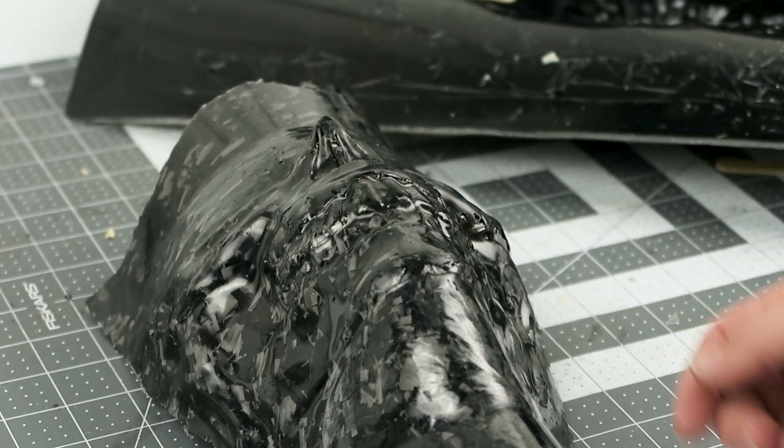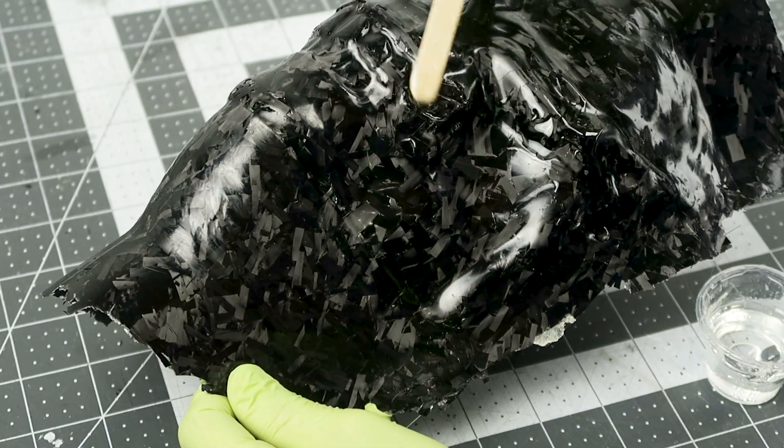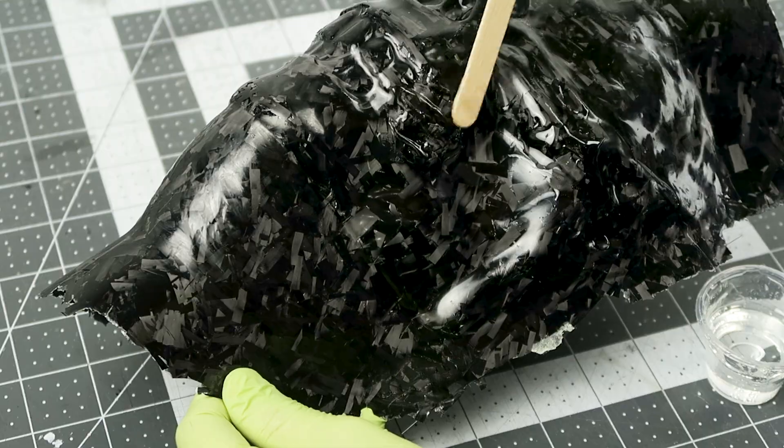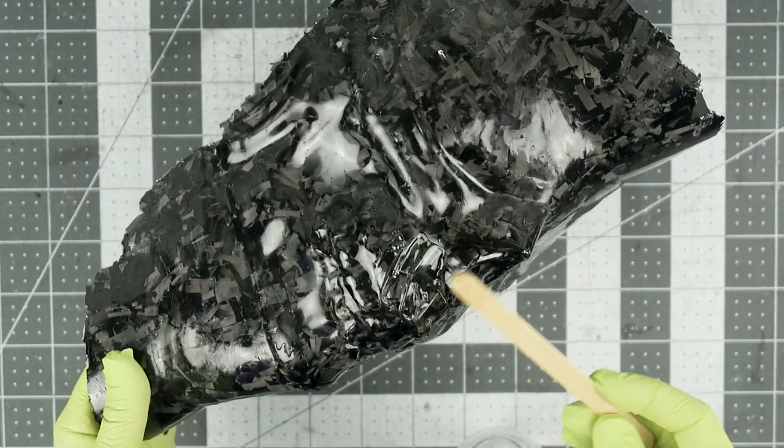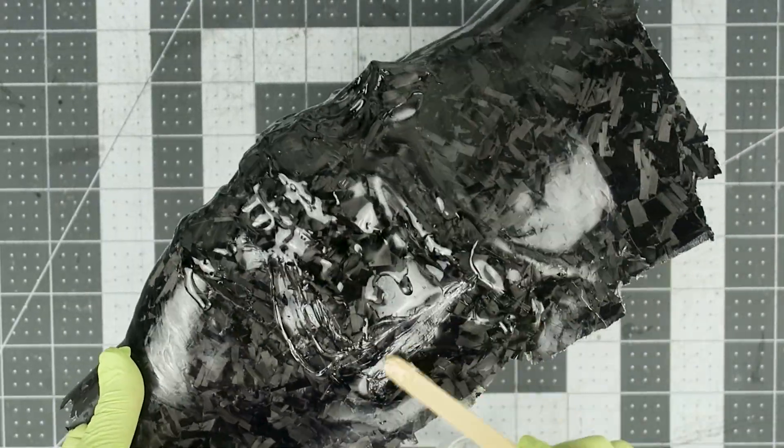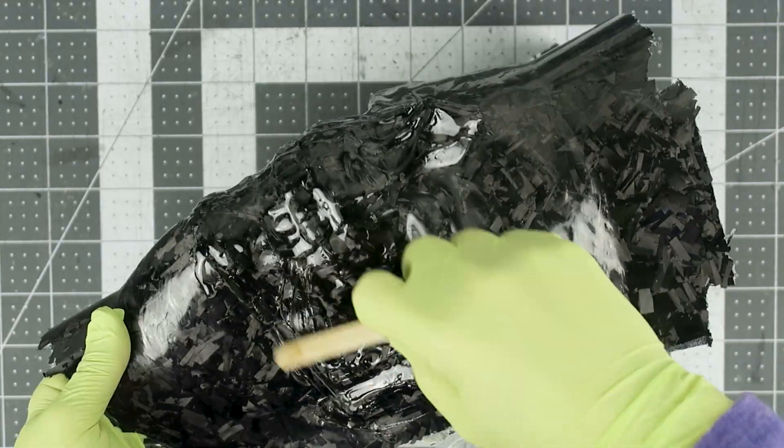It was from the same batch, but the mold for this was placed into a heated area so that it cured much more quickly, in about a day instead of three days. So then the leftover epoxy from the infusion was left to partially cure at room temperature.